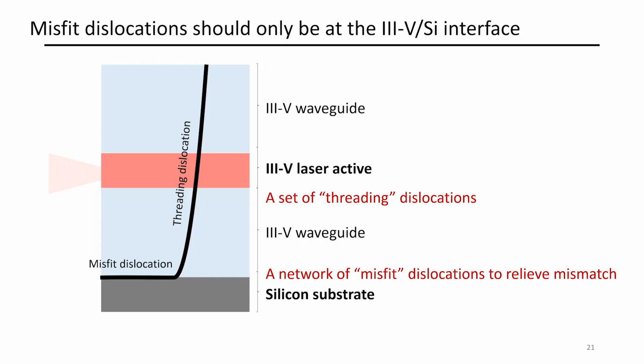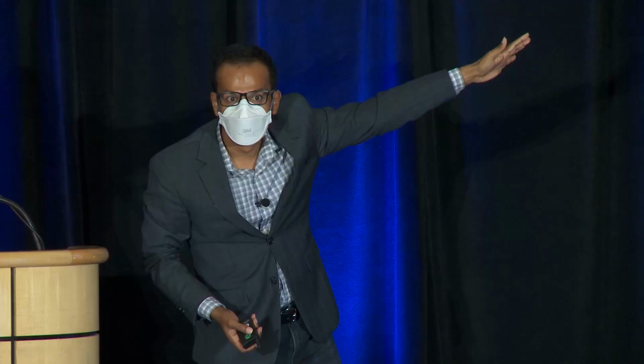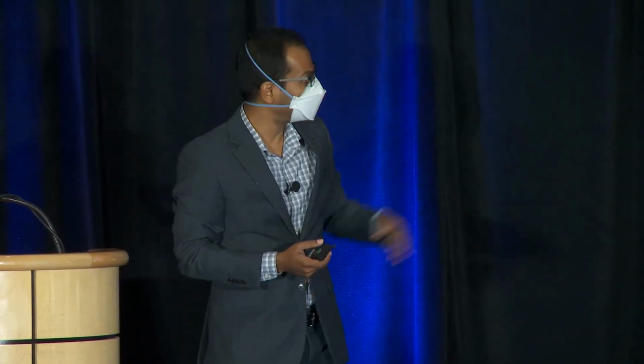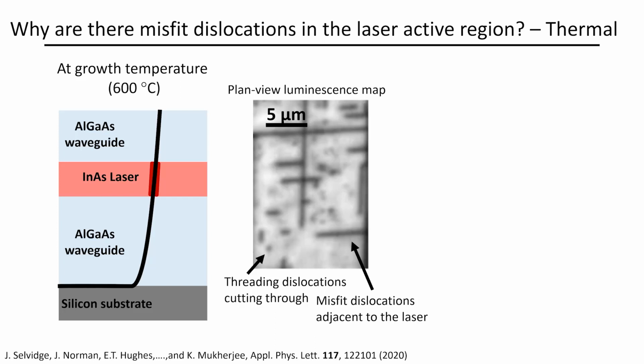But I want to point to something. We said that all the misfit dislocations, these horizontal segments, should be way at the bottom. We should have no dislocations up in that red region, which is my laser. Why do I still see dislocations up in the red region? And here's another view of it. This is the view of the laser. You see all of these dark lines. The dark lines up in the red region, not at the bottom where I want them to be.